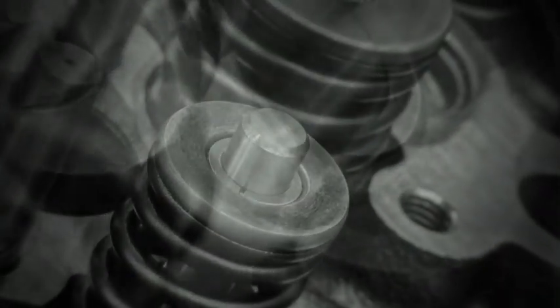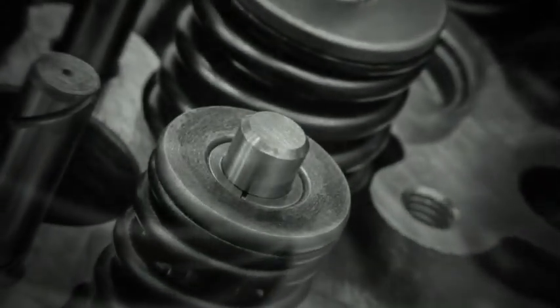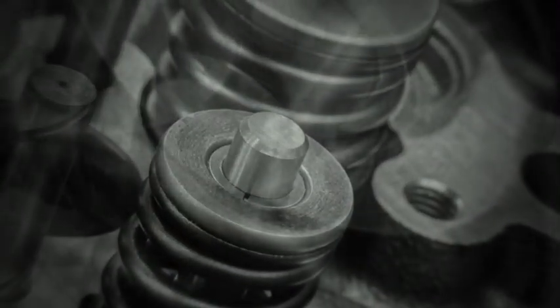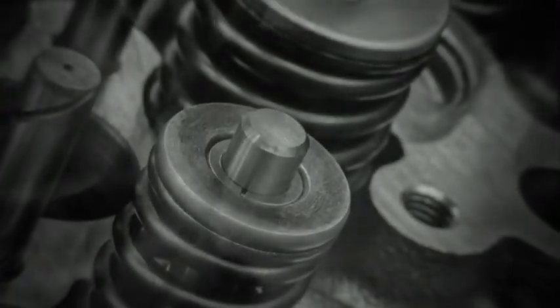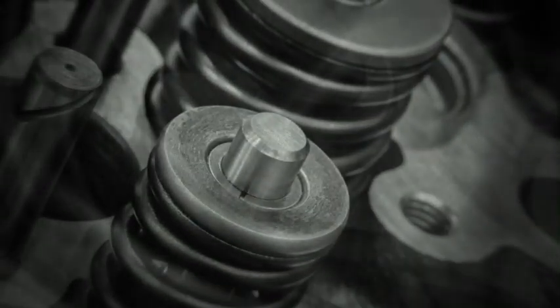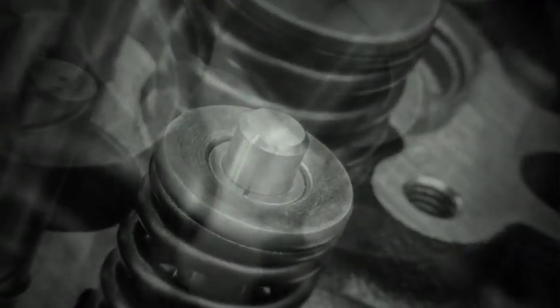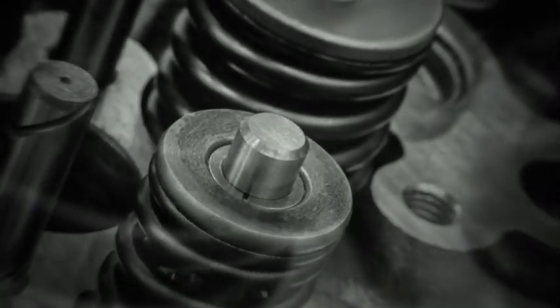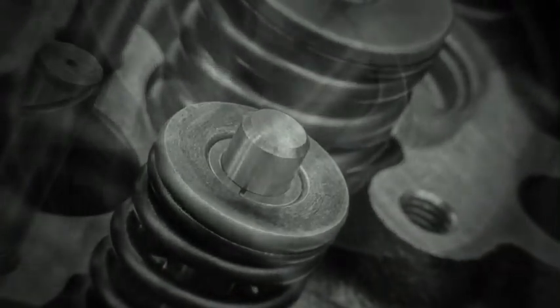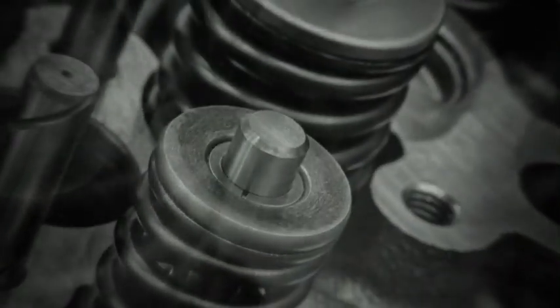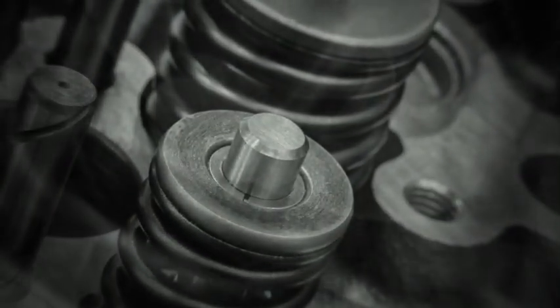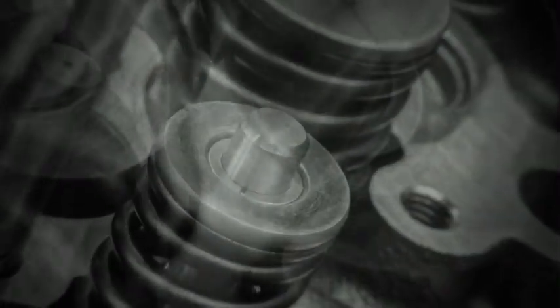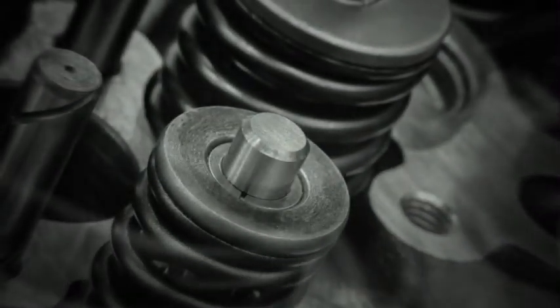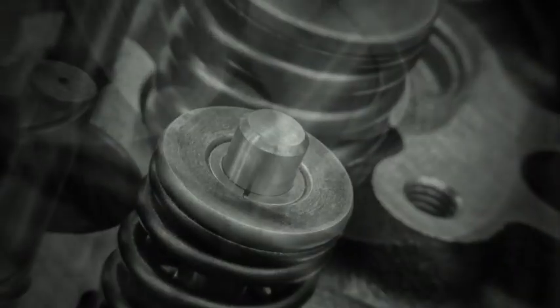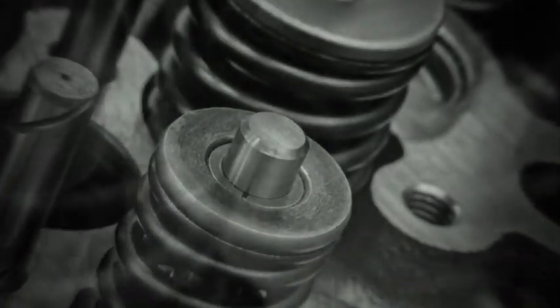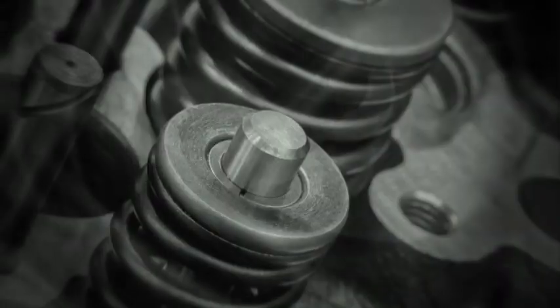A fracture near one end may point toward seating or surface damage. Several broken coils in similar positions across a fleet may reveal a design stress or manufacturing issue. Random failures after plating may raise concern about hydrogen. Loss of force without fracture may suggest relaxation or set. The spring should not be blamed merely because it is the part that broke. It may have absorbed loads created elsewhere.